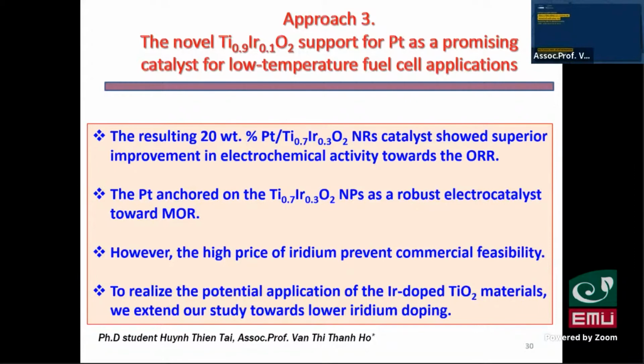For this topic, we use iridium oxide doped into titanium oxide with low doping. We have another study about zero-point-3 and also reduced the retained iridium to about 0.1 into the titanium oxide, because iridium is quite expensive. So the idea is to match low iridium loading into titanium oxide. We also apply this for MOR, methanol oxidation reaction.